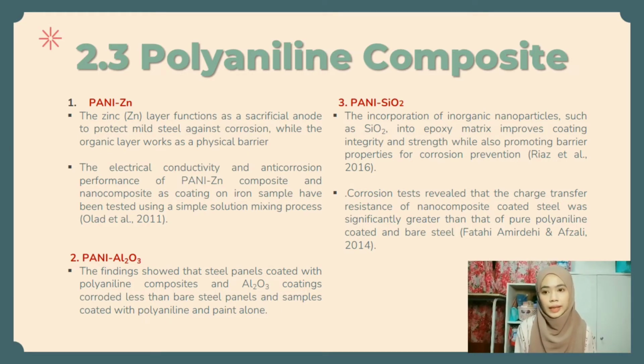The second one is the polyaniline aluminium oxide. The finding shows that the steel panel coated with polyaniline composite and aluminium oxide coating corrodes less than the bare steel panel and sample coated with polyaniline and paint alone. The third one is the polyaniline silicon dioxide. The incorporation of inorganic nanoparticles such as silicon dioxide into an epoxy matrix improves coating integrity and strength while also promoting barrier properties for corrosion prevention. Corrosion tests revealed that the charge transfer resistance of nanocomposite coated steel was significantly greater than pure polyaniline coated and bare steel.